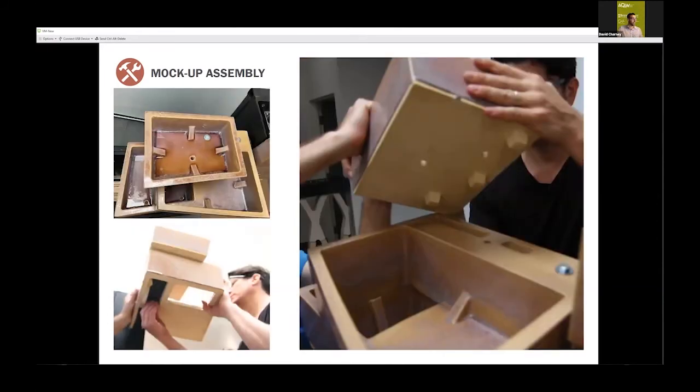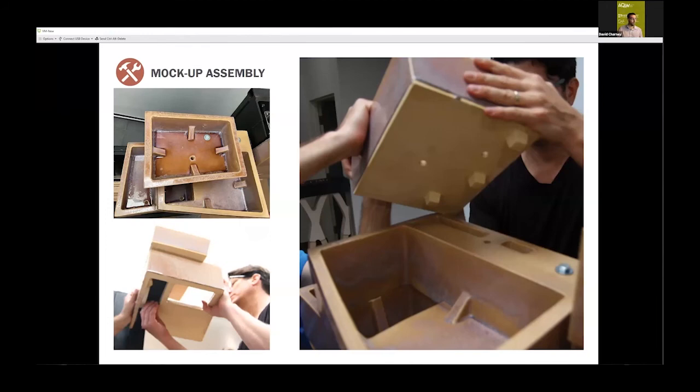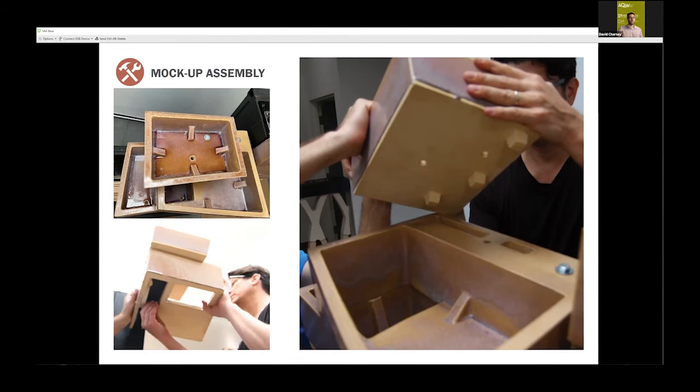Some of the complexities of the planter and manufacturing: you can see some of the draft angles required to keep the planter from being pulled out of the slip cast form. We had triangular pieces preventing it from collapsing in the drying process. You can see in the bottom left the tube that the middle planter slid on top of. There was a concern about the planter tipping, so the planter geometry helped alleviate that by putting the top planter on and gravity loading, changing the center of gravity for the system, which really helped.